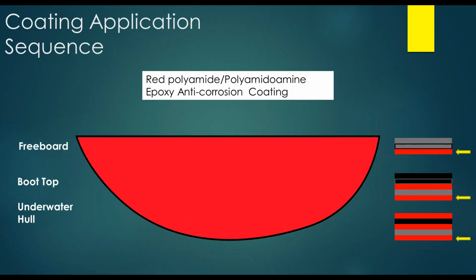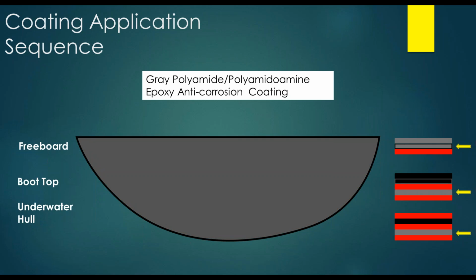Right now, I'm going to go through the coating application sequence just so that everyone's on the same page as to how this was applied. I would like to point out, for those of you that downloaded the preview presentation, that this is all consolidated into a single figure just for the ease of archival purposes. The first layer that was applied to the entire hull was a red epoxy anti-corrosion coating that had a polyamide and polyamidoamine hardener. A second layer of the epoxy anti-corrosion coating was applied that was gray. This is frequently done in a number of industries, using different colors so that the coating applicators or the coating inspectors can easily differentiate the different coating layers.